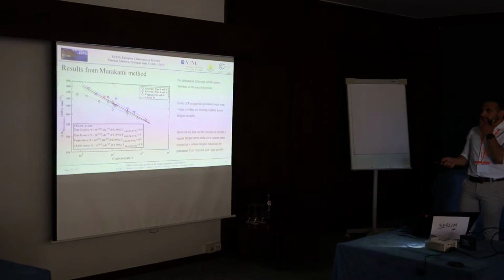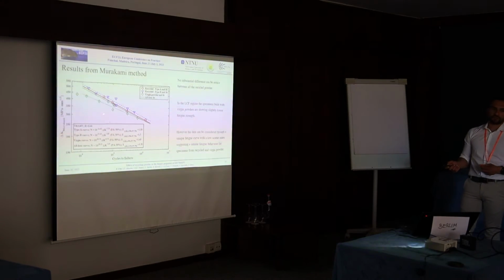If we summarize the data according to the Murakami method, considering now the range of the stress intensity factor, we can see that the data are more in agreement with each other. Indeed, the scatter of the data is significantly decreased, and actually it is already possible to consider all the data according to a unique fatigue curve.